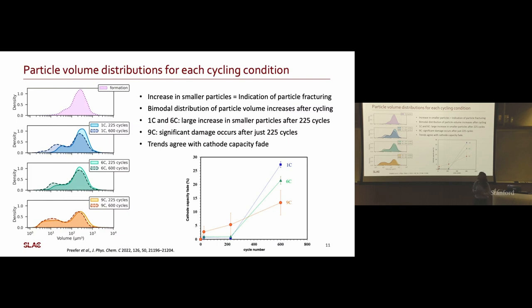So the next thing we looked at was particle volume for each of the cycling conditions. And so the density distributions of volume are here, the formation one, and then you can see the two different cycles, the 225 cycles or 600 cycles, for each of those conditions as they get faster and faster. And the thing you notice is there's a bimodal distribution after you cycle. So the formation cycle has just one peak. There's a bimodal distribution in 1C, 6C, and 9C. And that distribution actually changes between the 225 and the 600. So you're going towards more smaller particles. So there's an increase in smaller particles no matter what your cycle rate is.